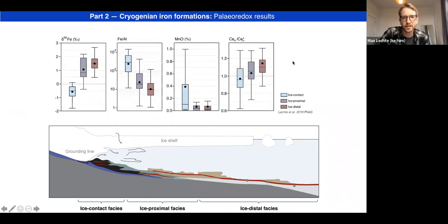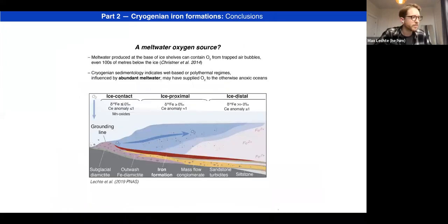And I won't really go into these data too much, but this is just to say that if you look at a number of other potential redox proxies from these iron formations and assign them to their different facies, you see the same trend emerges. So things like manganese enrichment, cerium anomalies, and so on. So this is all supportive of this paleoredox gradient where you have more oxidizing conditions becoming more anoxic as you move further away from the grounding line. So we interpreted this to represent a potential meltwater oxygen source.